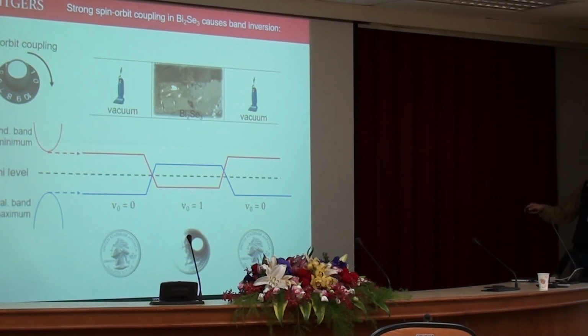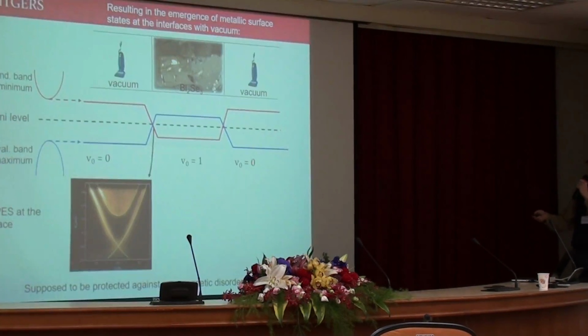So that's why at this stage, this bismuth selenide has different band structure topology relative to the vacuum. So you have the surface state, which is supposed to be guaranteed against any non-magnetic disorders. That is at least what is theoretically predicted, and experimentally confirmed by probes like angle-resolved photoemission spectroscopy. You have continuous surface bands, and this was the proof of the presence of surface state as predicted by theories.